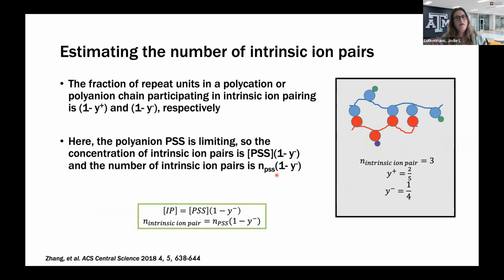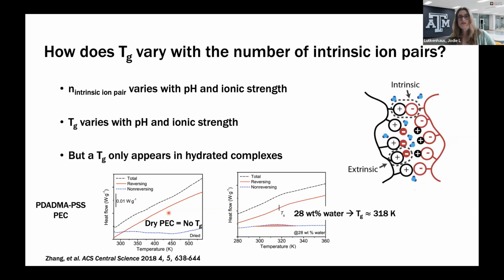With all of that data, we can estimate the concentration of these intrinsic ion pair crosslinks in the complex. We have to assume one of the polymers is limiting and the other one is in excess. This box over here shows how we can do that calculation. Essentially, we can estimate the concentration of the intrinsic ion pairs, or IP, as the concentration of the limiting polyanion times 1 minus the doping level. What we were proposing at the beginning of the presentation was that this concentration of intrinsic ion pairs is going to really play a role in the bulk macroscopic properties. I wanted to show you how we measure that, but now let's go measure some properties.